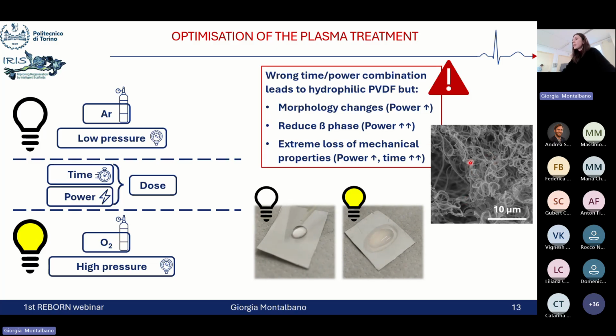So we can see here how high power levels can induce a detrimental effect in the morphological features of the patch, as well as a decrease in the content of the electroactive phase. And also, if we combine it with longer exposure time, we can also induce an extreme loss of the mechanical properties.